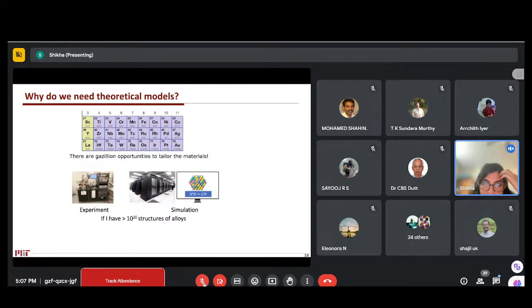In terms of performance, the only way forward is that we could mix the platinum with another metal atom, say rhodium, so that we could reduce the amount of platinum and still have the same activity or higher activity. So that is the idea.